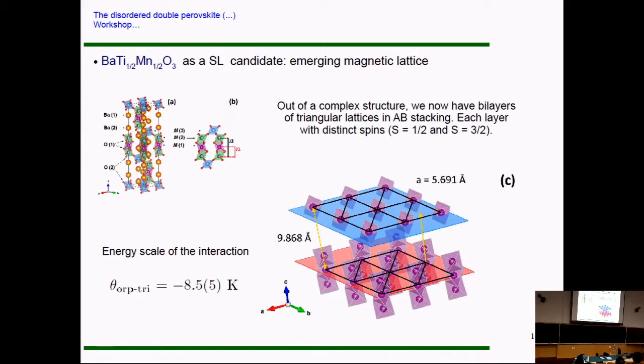If we do that, we realize that this very complex structure that we have at high temperature can actually be mapped into a new structure, taking into account only the magnetic degrees of freedom. That's what we are calling the emerging magnetic lattice, meaning you stop thinking about all the degrees of freedom which are frozen, because they form dimers, trimers, and so on, and you keep thinking only about this stuff here. If you go back to the structure and investigate carefully, you see bilayers of triangular lattice, in an A-B stacking, with these parameters here, and you have a lattice of S equal 3/2 spins interacting with a lattice of effective S equal 1/2 spins.